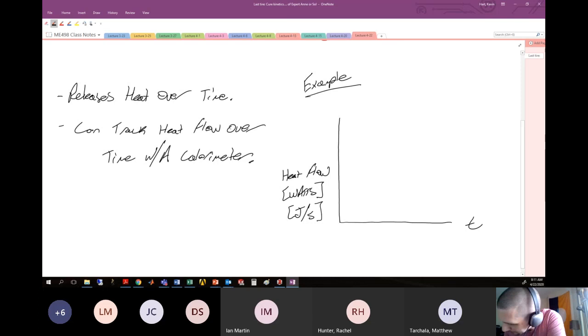Now, the way that this is going to go, and typically how this would work, is you take part A, you take part B, you mix them together in some way, some tin or some cup or whatever, and that cup is going to get hot. Now, it's not immediately all going to react. There's going to be some ramp up. Then there's probably going to be some peak in the rate of heat generation. And then it's going to taper off over time as all of the remaining molecules find each other and react together. So generally, you're going to have some ramp up, some peak, and it's going to taper out over time. That's generally what your heat of reaction is going to look like. We will typically label this function as W(t). This is the heat flow of the reaction as a function of time.